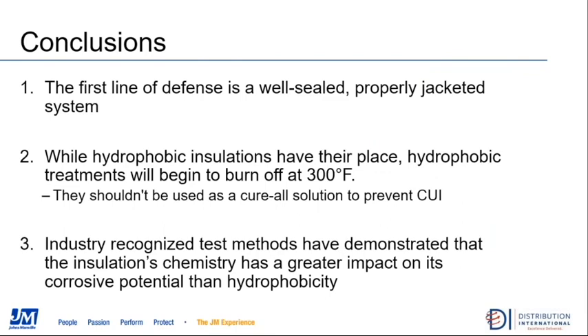So in conclusion, as Chad described at the beginning, your first line of defense really needs to be a well-installed, well-sealed jacket system over your insulation material. Very, very important to take a look at the properties of the insulation material you're selecting. Having a hydrophobic or water repellent insulation material has its advantages, but it's not a cure-all, and that needs to be taken into account. They're not going to be permanent and can only prevent the migration of water through the material itself, not provide protection if you get leaks at seams or joints in the insulation material. And as we've reviewed, there are industry recognized test methods that demonstrate that the chemistry has a much greater impact than any type of hydrophobic or water repellent properties will.